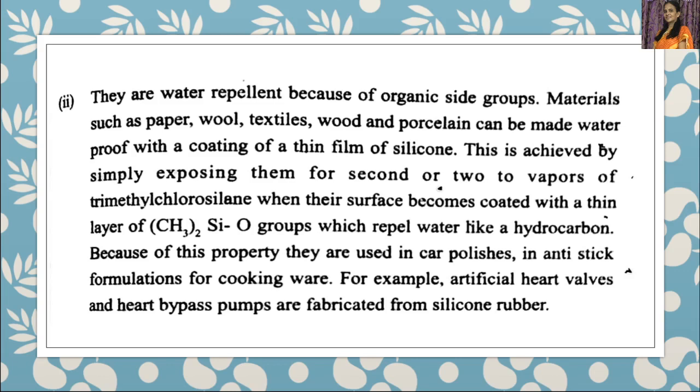And why are they water repellent? Because of the presence of organic side groups. And this is achieved by simply exposing them for a second or two, 1 or 2 seconds, to vapors of trimethyl chlorosilane. Their surface becomes coated with a thin layer of this group, which repels water like a hydrocarbon, like this group, when it is present on these particular compounds, it repels water like a hydrocarbon.